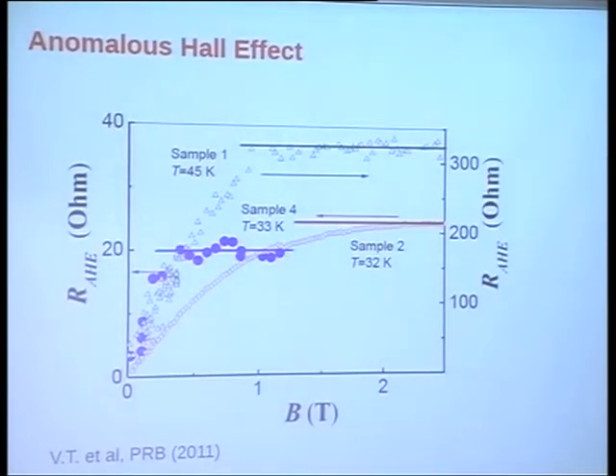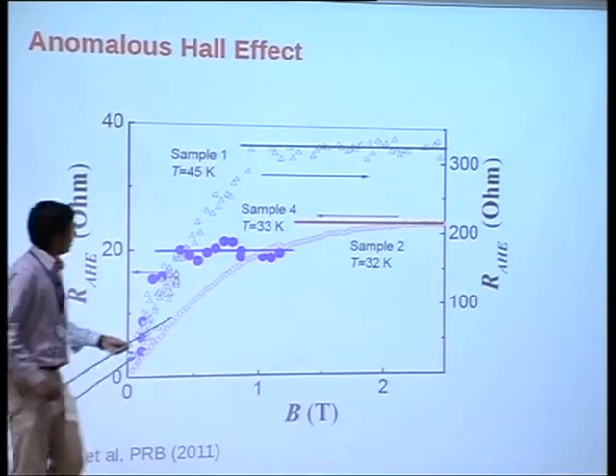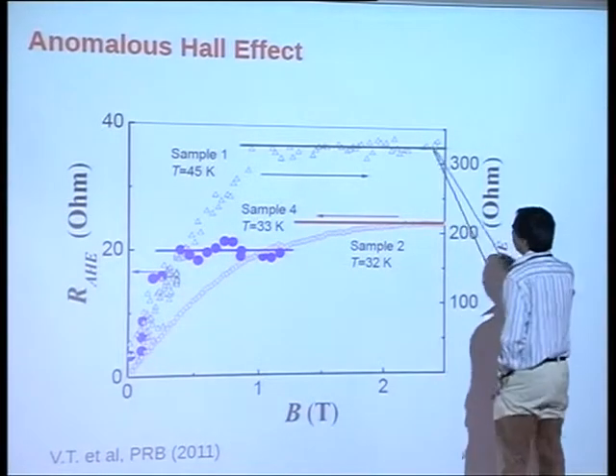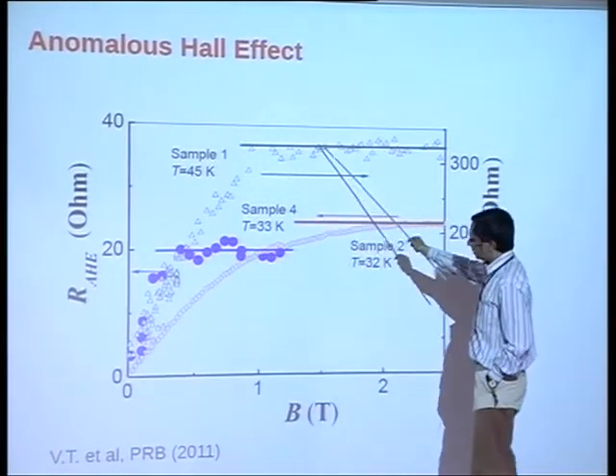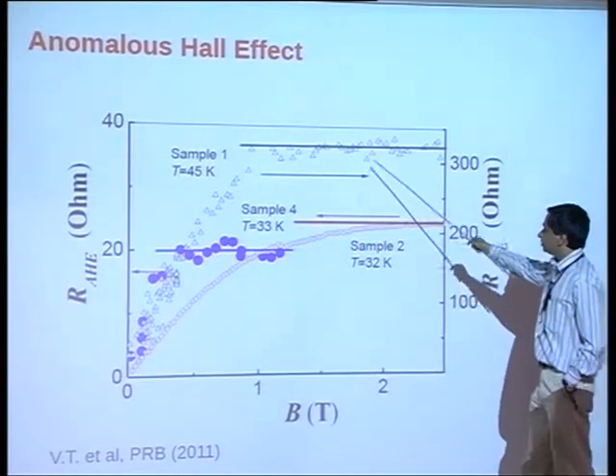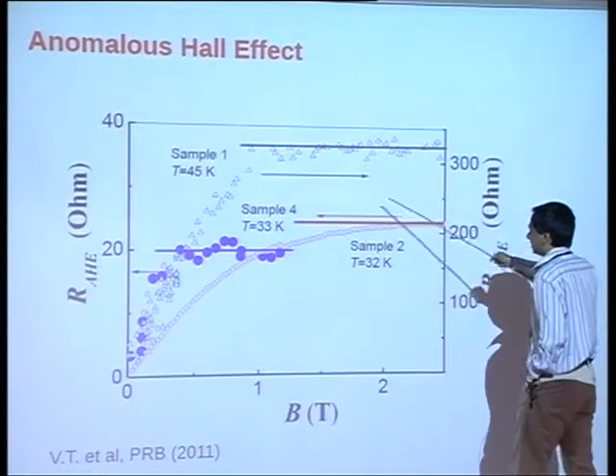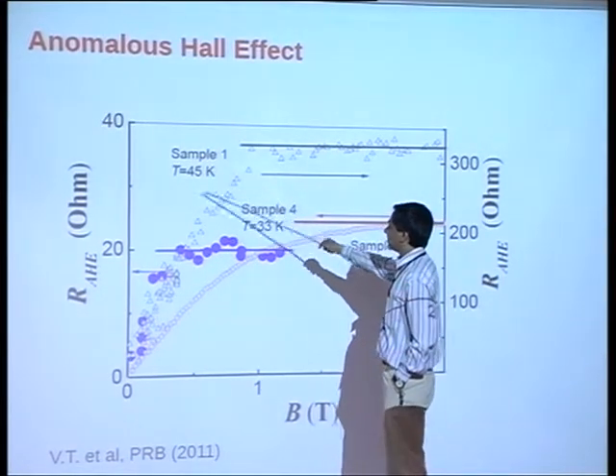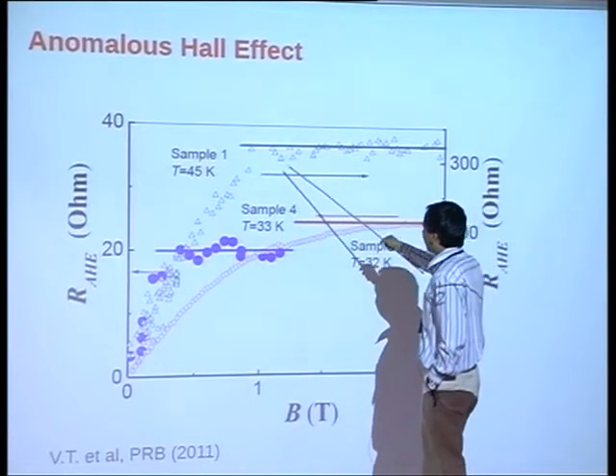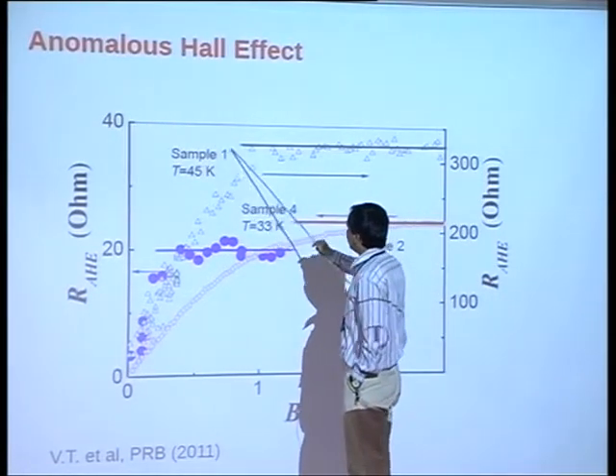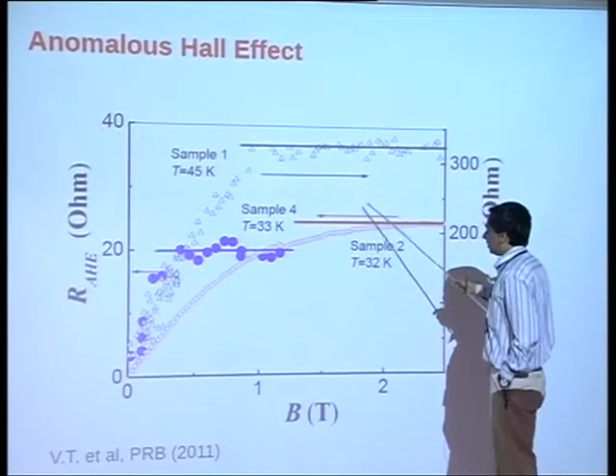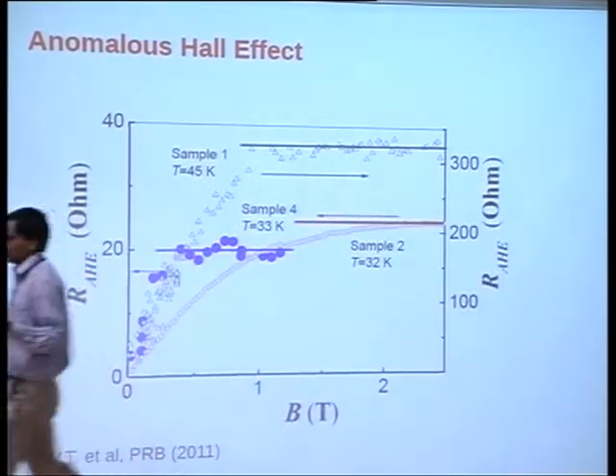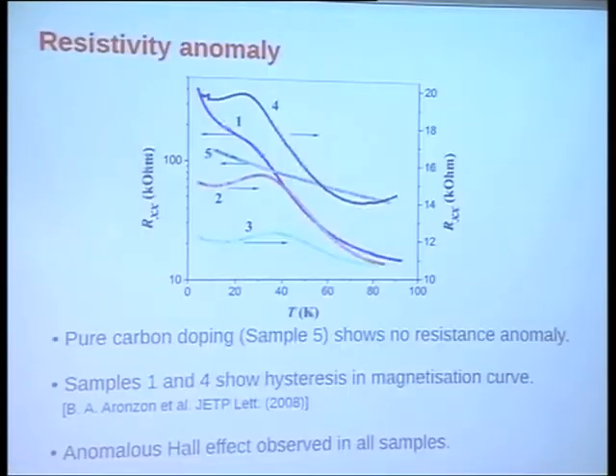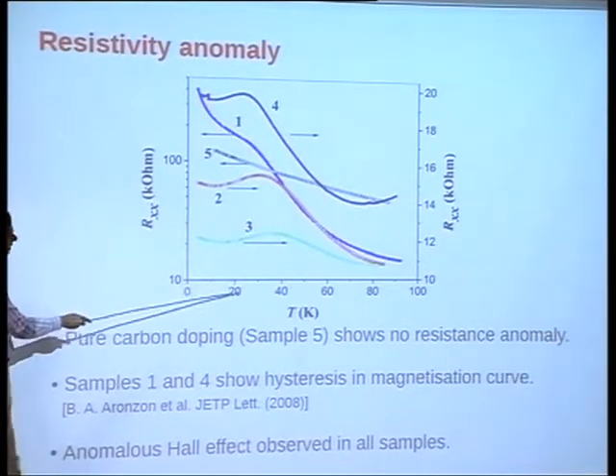So this is the most clear-cut evidence for ferromagnetism. This is anomalous Hall effect. This is the most heavily doped sample, and saturation of anomalous Hall effect as a function of magnetic field shows that this has gone ferromagnetic, and it's at a relatively high temperature of 45 kelvins. We don't have data on yet higher temperatures. Maybe it went ferromagnetic even higher, but see that these temperatures are way above the temperatures at which anomalies in the resistivity are seen, which are around 20-25 Kelvin.